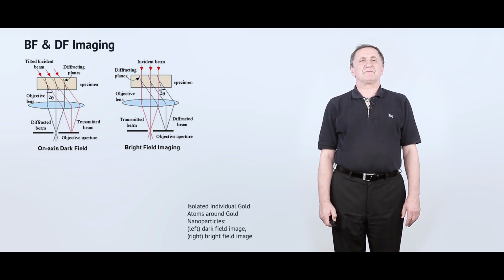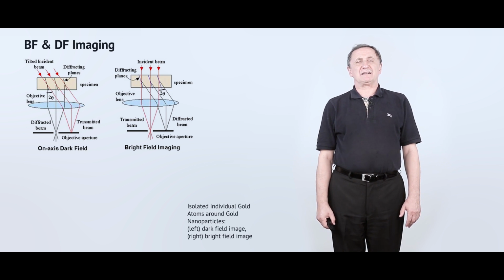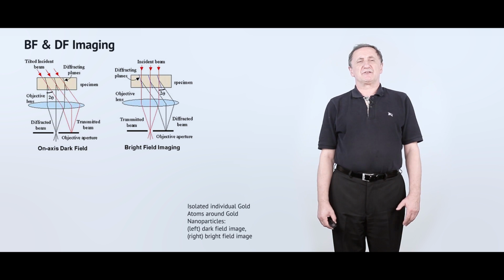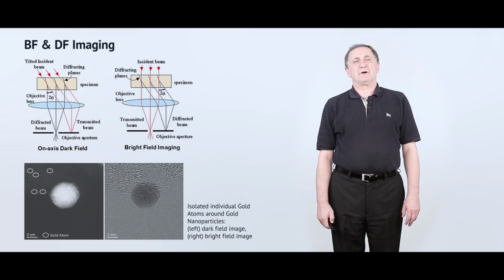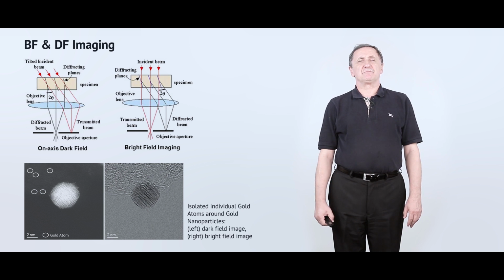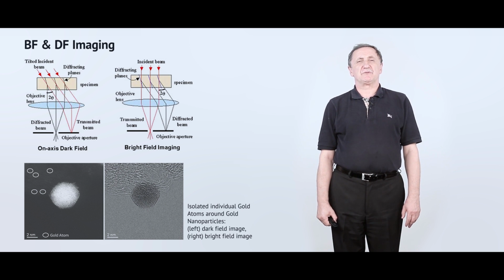On the left side, we have the so-called dark field image, where the diffracted electrons were detected, the electrons which significantly change their direction as a result of interaction with our sample. Again, it's clear that many more electrons will diffract from or in the vicinity of the gold particle as compared to the extremely light carbon. That's why on the dark field image, the gold particle looks much brighter as compared to the carbon. Understanding the physics of the interaction between the electrons and particles is very important to provide the right interpretation of the obtained results.